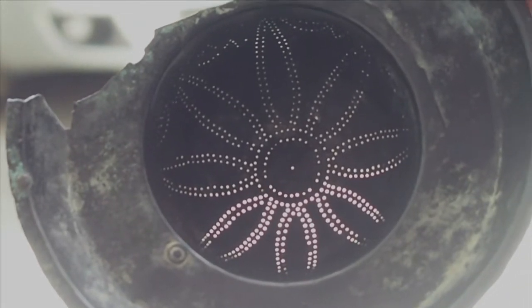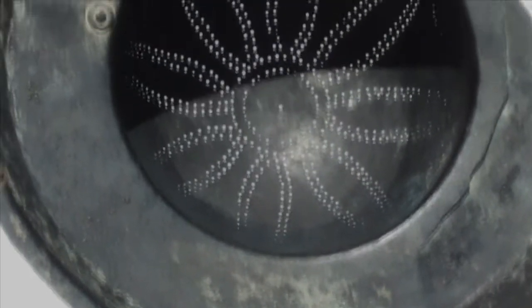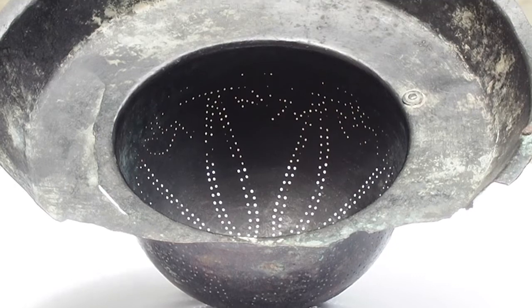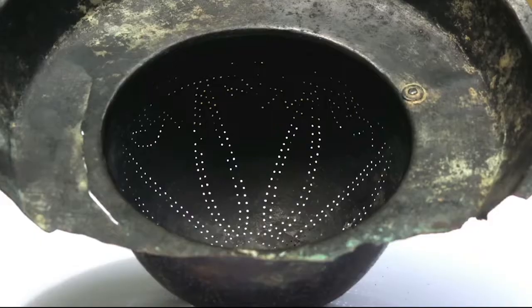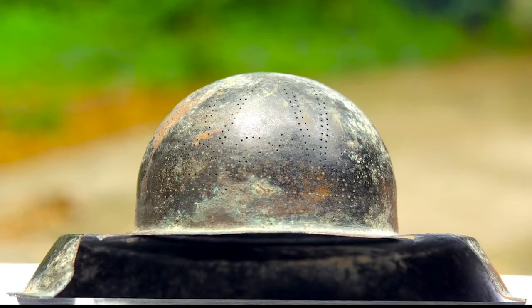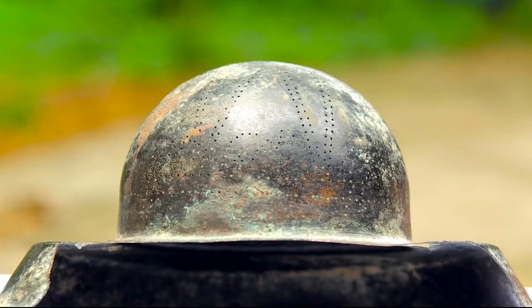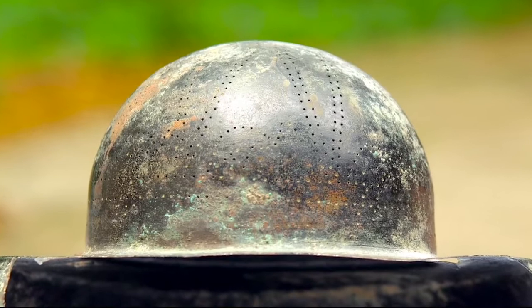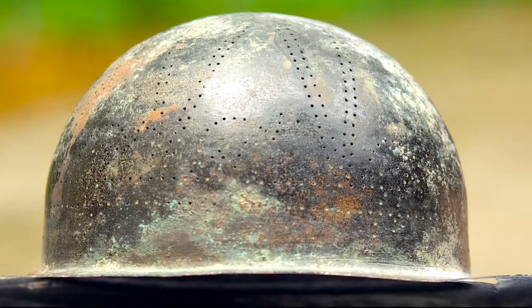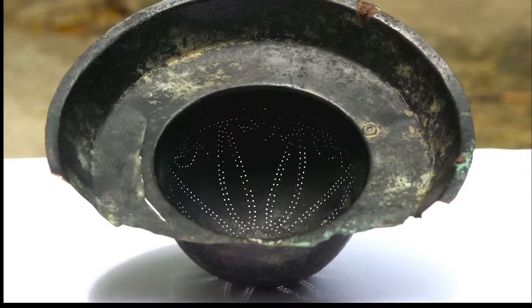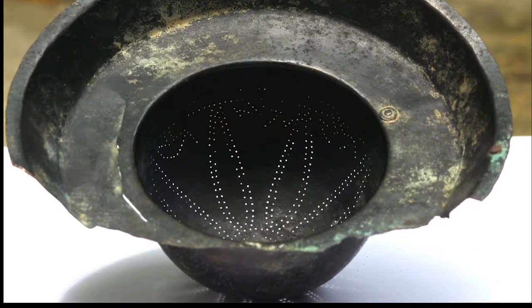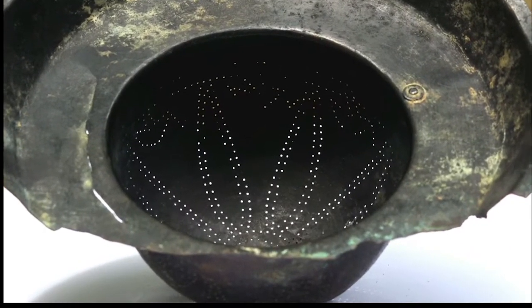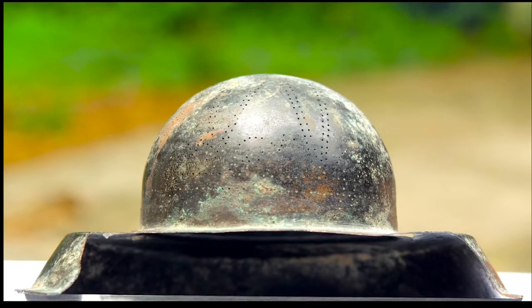We can understand now how this exquisite megalithic artifact of Kodumanal, of hot forged and quenched high-tin bronze, was made and hollowed out to such perfection, with very fine perforations made of extraordinary thinness of about a tenth of a millimeter. Bronze with a composition of about 23% tin can be forged to a very high degree, between 650 and 750 degrees centigrade, due to the formation of a beta phase, which seems to have quasi-superplastic properties and can be forged to a great degree.